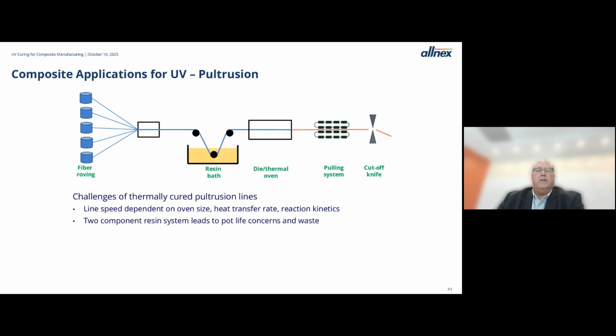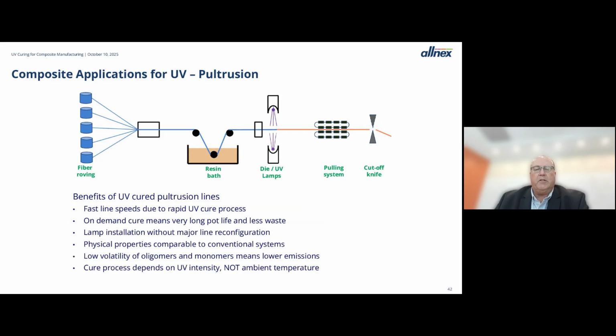Similarly for pultrusion, the diagram's not quite as pretty, but still you get the glass fibers, collect them, they go through a resin bath. With a thermal system, this goes through a thermal die. And so the line speed is going to be dependent on how big that oven is or how big that thermal system is, the heat transfer rate, the reaction kinetics of your system. If you want to change to UV, you remove the thermal oven and put in UV lamps. So converting a line to UV is not a terribly difficult thing.